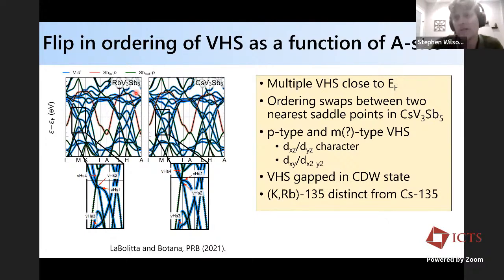First of all, the charge density wave superstructure seems to be different. And this also seems to correlate that as you insert this larger alkali ion between the layers, at the same time, you also flip the ordering of the Van Hove singularities, which are closest to the Fermi level. And so you end up with this dxz, dyz, which ends up closest in the cesium variant versus the other two. Okay, so there's this subtle switch in the ordering of the Van Hove singularities near the Fermi level, and that corresponds to the onset of seemingly a different pattern of charge density wave order.